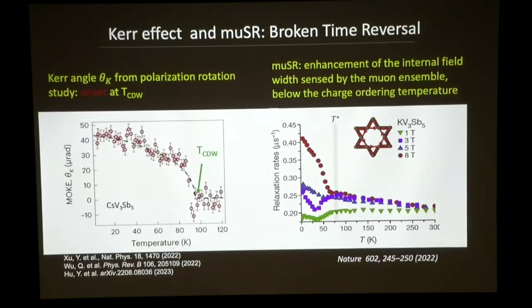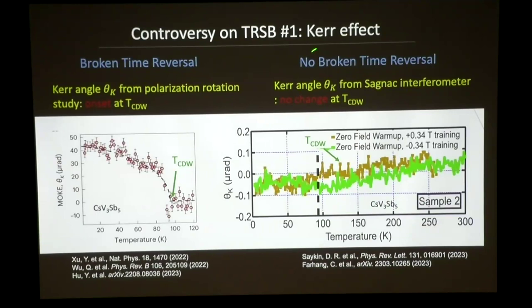The first controversy comes from Kerr effect measurements. Again, you don't have to know the details. They measure this parameter theta, and you can see below the CDW transition, this experiment shows that there's a change in this theta, whereas this experiment shows no change across the CDW transition. So two different experiments showing completely different results.